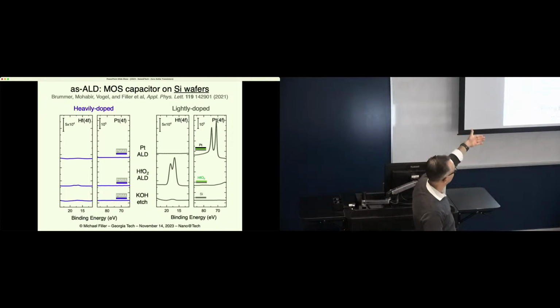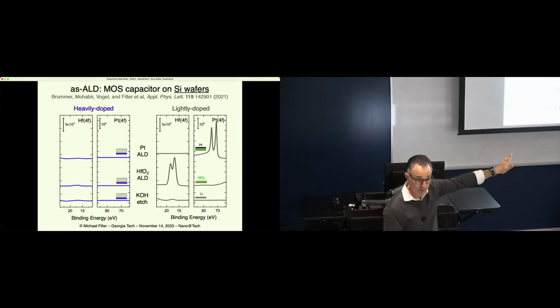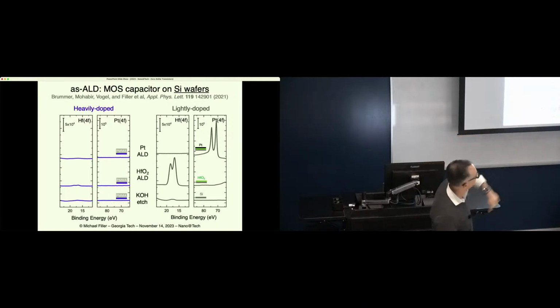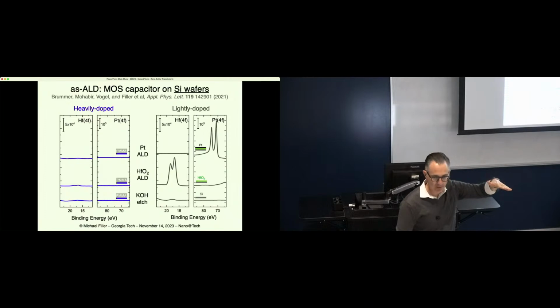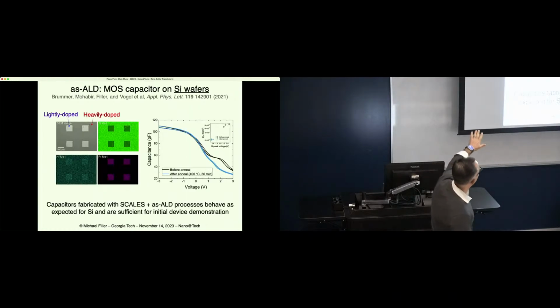And then the next step will be a hafnia process that we do here at Georgia Tech. And we can see that hafnia goes down on the lightly doped region, which was the one that we had just exposed, and it's pretty much blocked from the heavily doped region. And then we can apply the platinum process, and we can put platinum on top of the hafnia, and we don't get much platinum on the heavily doped region.